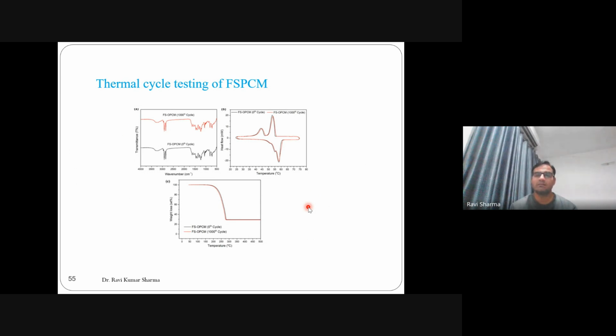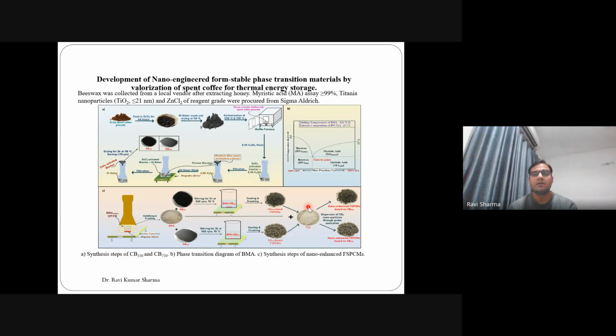The thermal cycle test was also done for 1000 cycles, and the material was pretty stable thermally and chemically after 1000 cycles. And there's another work that we did.